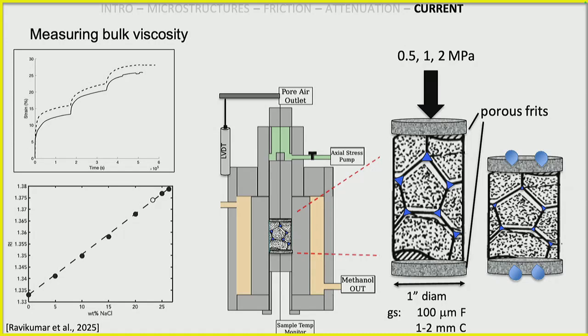He's got a couple ways that he can monitor it. One is that there's an LVDT that's measuring the shortening over time. He also can weigh the frits before, when they're bone dry, versus after, when they're soaking wet with all this saline. Also, a last method we use, which we love, is that we can take a representative chunk of the sample, melt it down and put it in a refractive index meter, which tells us the degree of saltiness, which we've calibrated. And he's found that, if his samples start here, they end way down. I don't think down to 0, but very low.